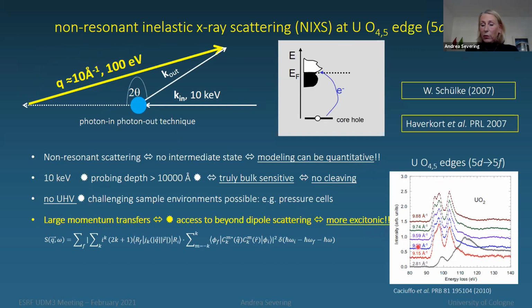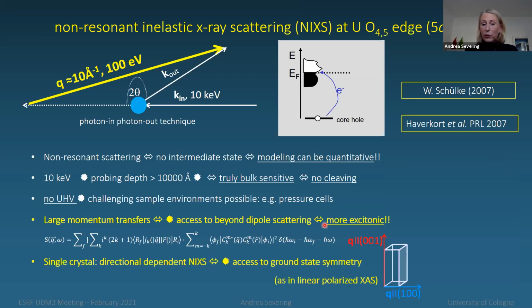Also something you have seen before from Roberto. These are Roberto's data on a polycrystalline uranium dioxide sample, intensity versus energy loss. Here at low momentum transfers, you have a very broad O-edge spectrum. It looks almost like an X-ray absorption spectrum. And if you go to the high momentum transfers, you have these extra excitations at lower energies, further away from the continuum states, and that's why they're more excitonic. And these we can model very nicely. And we can actually use this in order to do, for example, a single crystal experiment.